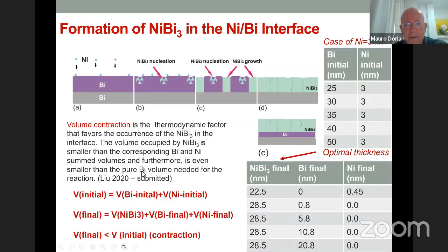I mean, this system you have to have under thermodynamic control. I think it has to be at room temperature, I don't remember exactly. At the end, it's something like ice. When you form ice, you have an expansion of the volume. We know that: you put water into the freezer, and the water gains volume. Here it is just the opposite. You put these compounds, they form this one here, perhaps because of this argument that you have some volume contraction.